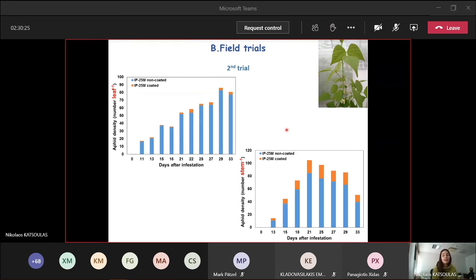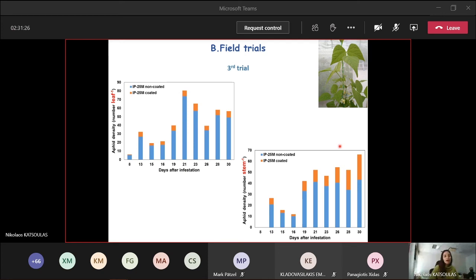Here, as I said before, bean is considered a more susceptible plant to aphids. In the first graph, you can see that the infestation on the leaves was much higher compared to the coated net. When we have 70 aphids per leaf on the control treatment, only 7 aphids were found on the leaves grown on the coated net. And in this graph, you can see the results obtained from the stems evaluation, where the infestation was much higher compared to the leaves. But still, you can see big differences when we compare the number of aphids on the coated and non-coated nets. And finally, here you can see the results of the third trial, where you can see again the differences between the two nets.